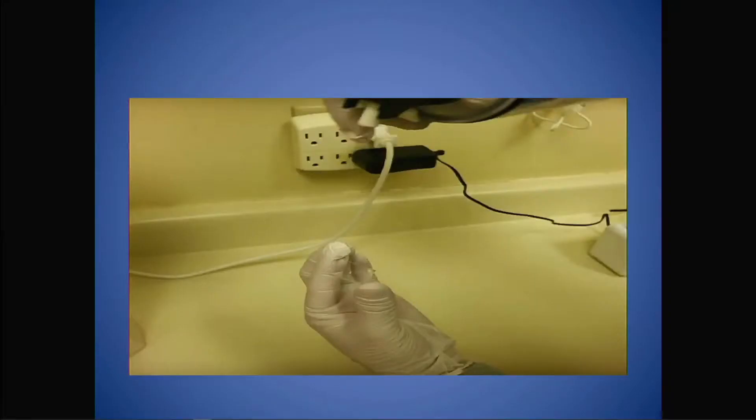There was an internet rumor that the temperature of the fluorocarbon propellant is minus 100 degrees Celsius. If that were the case, you'd end up having microfractures in the glass and also in the coatings. So I took a digital thermometer — I was curious to see how cold it really was. It's only about minus 38°C, so it's not really quite that dangerous.